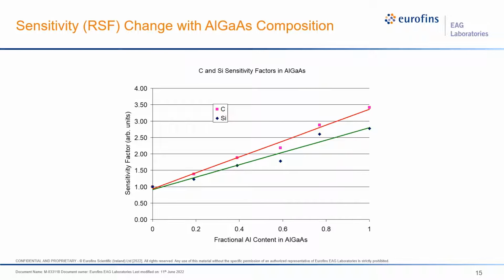Now I should note on the slide that the vertical axis is relative sensitivity factor. And this is a term that is needed in the quantification, but you should realize that there's an inverse relationship between relative sensitivity factor and sensitivity. So as the aluminum composition goes up, going from left to right on the graph, the sensitivity of carbon and silicon actually go down. And as we shall show, VCSELs have aluminum content varying from 10% to 99% group 3 atom fraction. So these differences in sensitivity need to be accounted for. If not, seriously inaccurate doping concentrations will be reported.